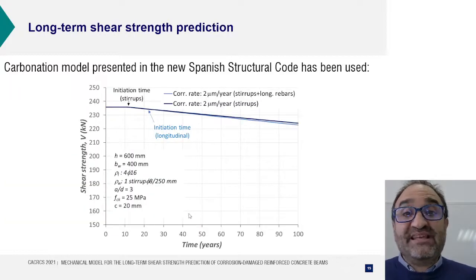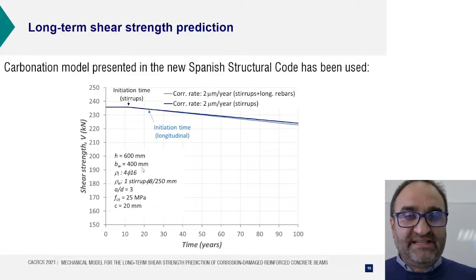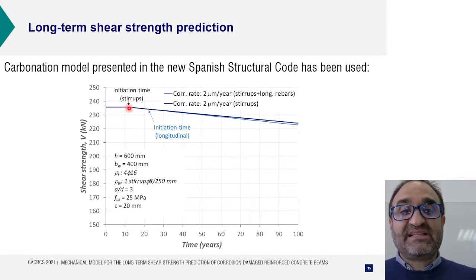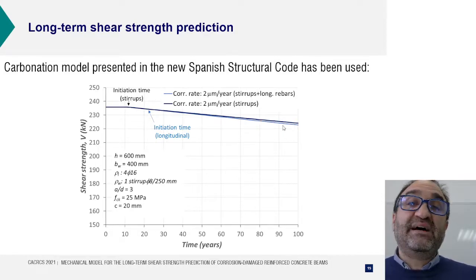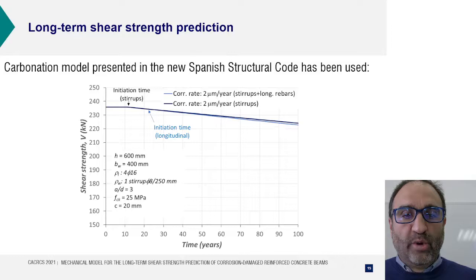Well, here you can see what we are now able to do, that is, for a beam with a given geometry, to have the original shear strength, and then to study after the initiation time, when carbonation corrosion starts affecting the stirrups, and then we also have the initiation time for the longitudinal reinforcement. And you can see here that the shear strength degrades, especially when we take into account the stirrups. We are also considering the longitudinal rebar corrosion, but the influence is of course lower.